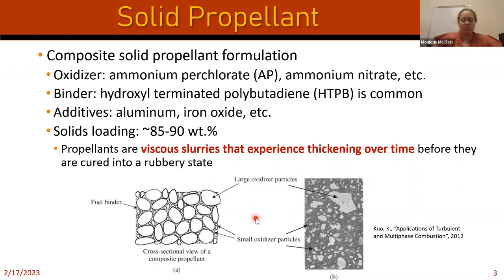When we work with these types of materials, in general, the particle content, so your solids loading or volume loading, will increase the viscosity. Your coarse to fine ratio of your particles can also change that. If you include things like nano additives, that will obviously make it more viscous as well. So in general, these propellant slurries are very viscous. They also harden over time because of the isocyanate. So processing this material can be a challenge, especially if you want to make certain types of shapes.